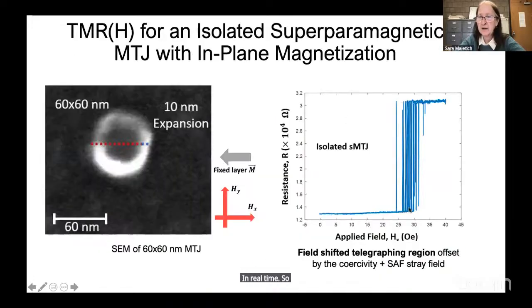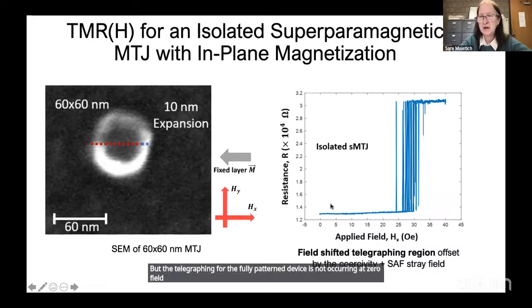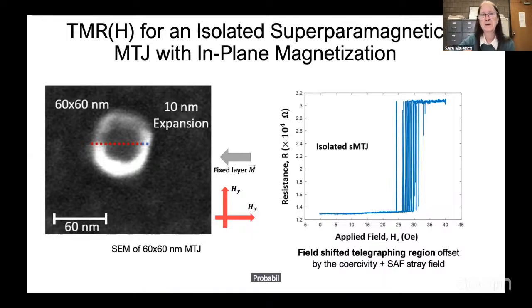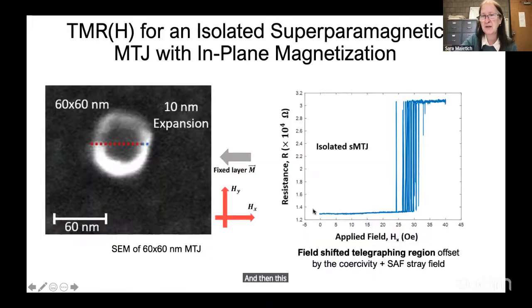So we're seeing this telegraphing, but the telegraphing for the fully patterned device is not occurring at zero field, where it would be low energy, but at 25 to 30 Oersted, where you'd have to apply an external field to make this work for probabilistic computing. You don't want that. If you go back and you don't pattern this fixed layer, then the fringe field drops down from 30 Oersted to just a few Oersted. And then this telegraphing region extends across 0. So that's an important trick.